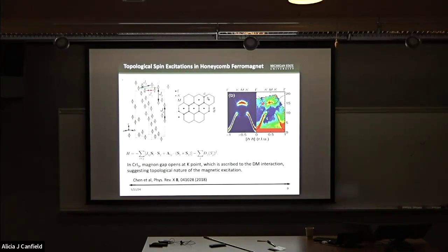And since it has a honeycomb lattice, the inversion symmetry is broken relative to the second-nearest-neighbor bond. Therefore, the DM interaction is allowed. And from the inelastic neutron scattering study, we can see that there's a magnon gap opening at the K point as well, which is very similar to the copper 1,3-BDC that I showed you earlier.